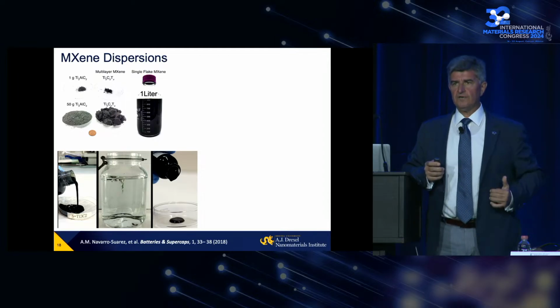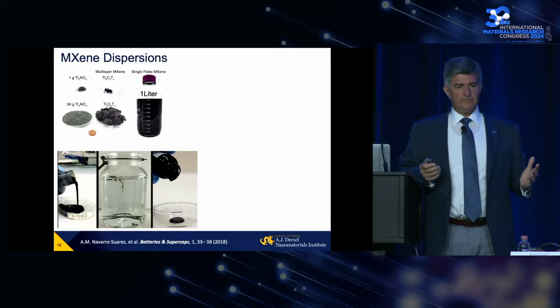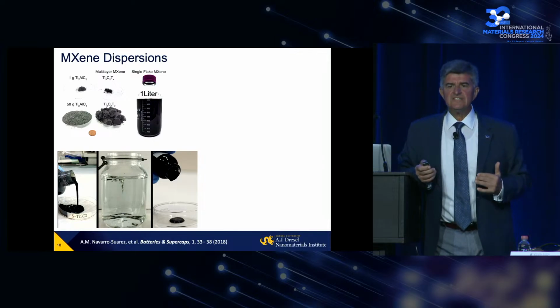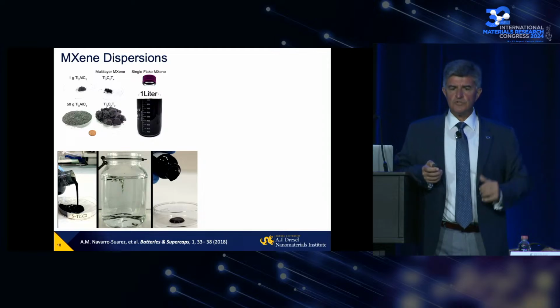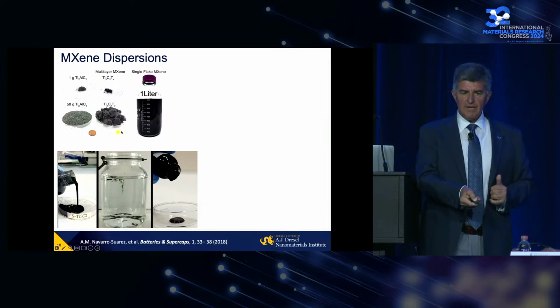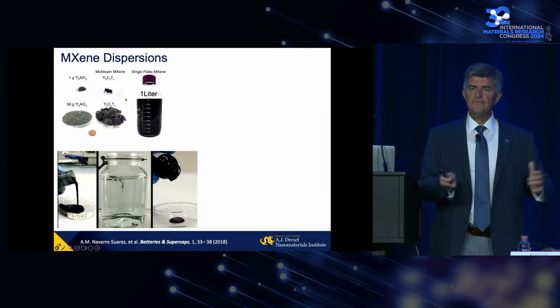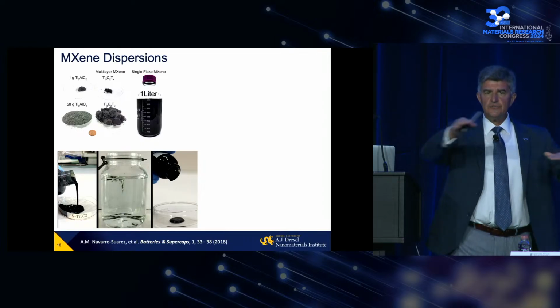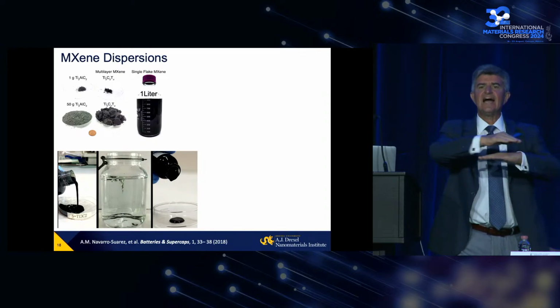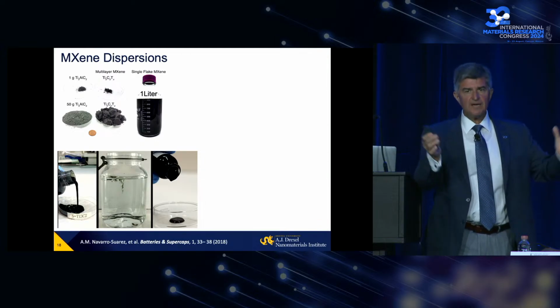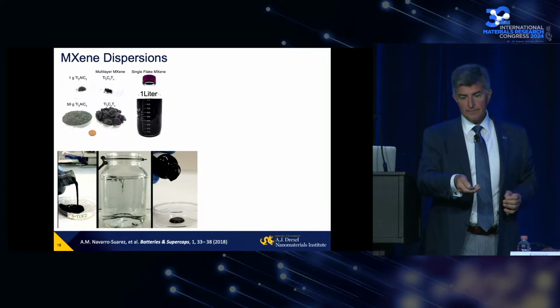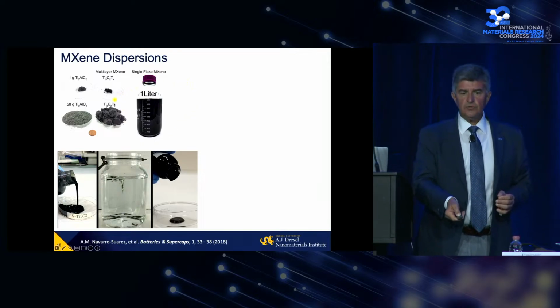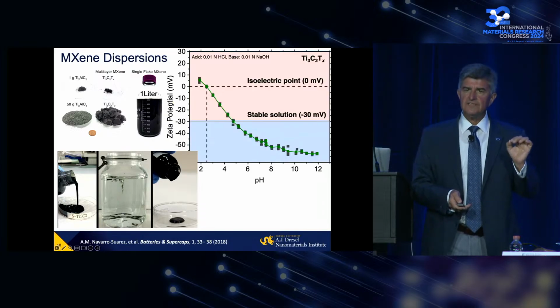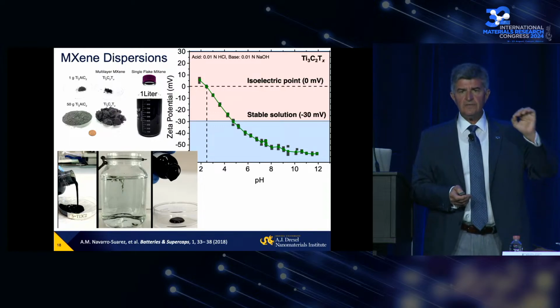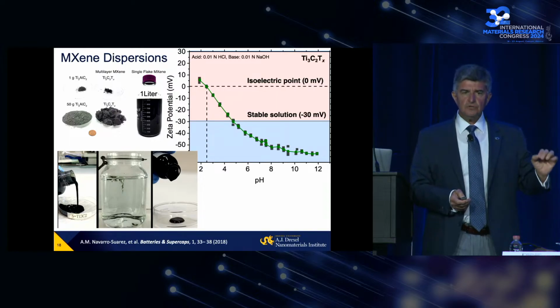Moreover, there is one more important factor: processing. I already mentioned that if we do selective etching to make MXene and get oxygen and hydroxyl groups on the surface, we etch the ceramic, making something called MXene clay, because rheologically it's really like clay. After etching, with lithium or sodium ions between the layers, they can slide with solvated ions like a clay. You can make a pot out of MXene, or a coffee mug, but just like clay, just like graphene oxide, you can disperse it in pure water - no surfactant needed. This is a big difference compared to graphene or dichalcogenides, where you need to use surfactant, burn it, or use metal nanowires for conductivity.